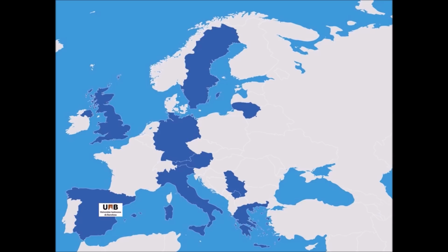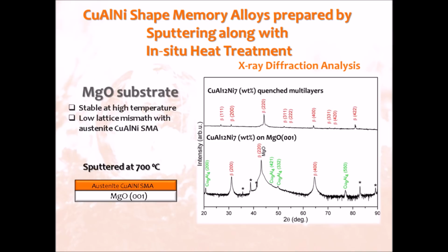To figure that out, I made a visit to another partner of the network, University of Cambridge. There, fellow PhD candidate Semerkardi and I worked on sputtering of this system along with in-situ heat treatment. Magnesium oxide with 001 orientation was chosen as the substrate due to being stable at high temperatures and its structure that favors the epitaxial growth of the austenitic phase. It was shown that austenitic copper aluminum nickel could be obtained by this method as well.